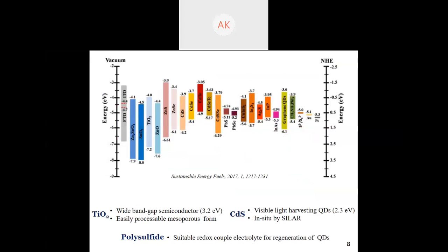Also, there are a few wide bandgap semiconductors which possibly can be used or have been used previously. I use TiO2, which has a bandgap of 3.2 electron volts. It's easily processable in mesoporous form, but there are people who use ZnO or SnO2 as the case might be. Now, for the quantum dots, I use CdS, which is a visible light harvesting quantum dot, 2.3 electron volts. There are also a variety of others which are listed.